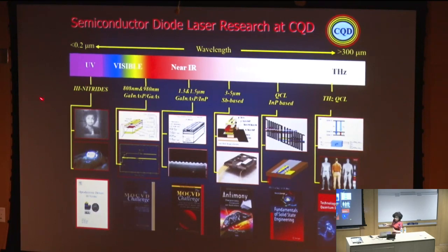In the case of the UV, I explained already. In the case of the 808, 980 that all of you are working with, the material, aluminum gallium arsenide, was not reliable and was very expensive; for each watt of power, it was more than $1,000. I developed the new material, aluminum-free, ternary, quaternary, at the same time as the MOCVD that I created with the device, that I published in Nature when I came, and immediately the patent, and it went to production. Everything is in my book, MOCVD Challenge Volume 2. All of the information is here, so I'm not going to speak about it.